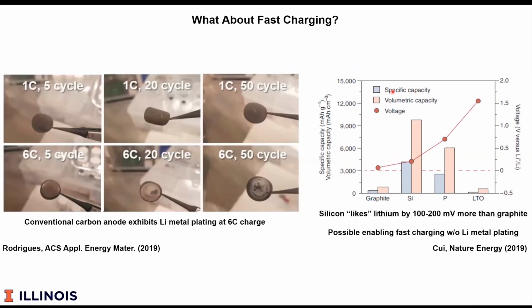So if you take a conventional carbon electrode, that's the one down at the bottom here. If we charge it at a normal rate, say 1 hour, we really don't observe any lithium plating. This is just a coin cell that's been dismantled. On the other hand, if you do fast charging, so this is a 10-minute charge, even after 5 cycles, it looks silvery, and certainly by 50, you can see the lithium dendrite.